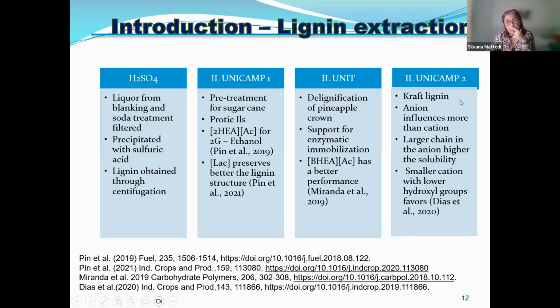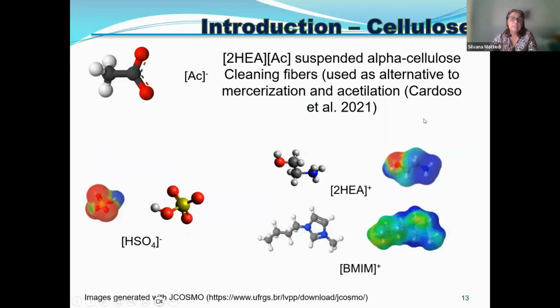There is a work from Unicamp with João Coutinho's group, from Aveiro, and they studied kraft lignin, and they concluded that the anion influences more than the cation. If you have a larger chain in the anion, the solubility is higher. If you have a smaller cation with fewer hydroxyl groups, it also favors the solubility of lignin. But we are interested in cellulose.